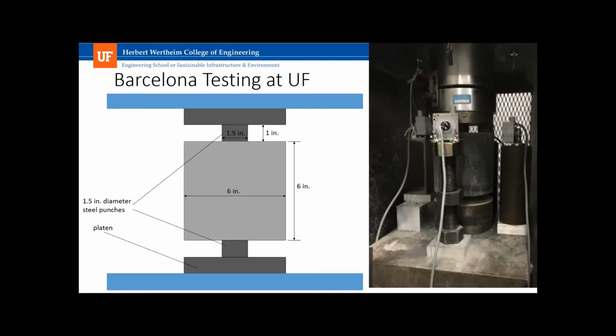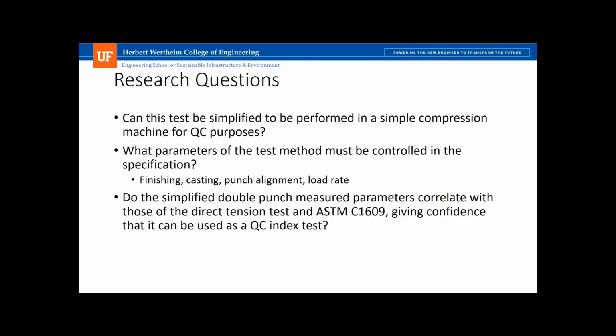So we started testing a program where we used, you can see here, some string potentiometers to measure the axial displacement of our machine and measure the load, and we're able to capture a load axial displacement curve for samples tested in our simple compression machine. Okay, so we wanted to answer as part of this, can this simplified test be performed in a simple compression machine for QC purposes? Does it work? And is it going to give you reliable results, even though it's not a closed loop?